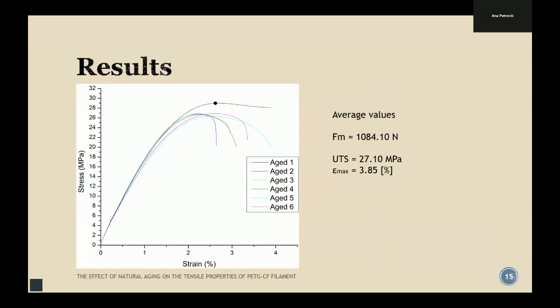Here is the stress-strain curve. Only one aged sample, sample number 4, has slightly better results than the rest. The other 5 are also the same. When we get average values, we get a maximum force of 1,000 newtons, ultimate tensile strength about 27 megapascals, and maximum deformation about 3.85%.